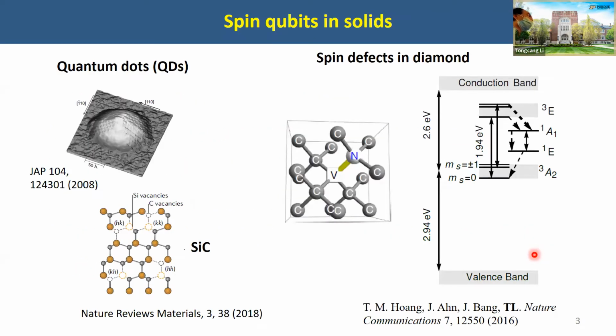Okay, so there are different kinds of spin defects in solids. One would be quantum dots, and silicon carbide, but the most famous one would be the spin defect in diamond. In particular, the NV center, which is formed by substitution of a carbon atom by a nitrogen atom and a nearby vacancy. And the electron can be trapped in the vacancy. This will form nice energy levels. Diamond is a very wide band gap material. You have a valence band and a conduction band. The band gap is about 5.6 eV.